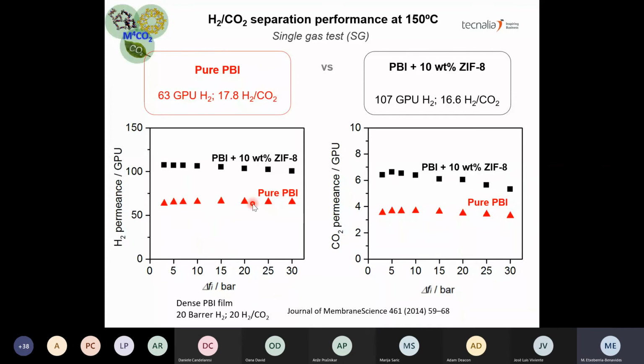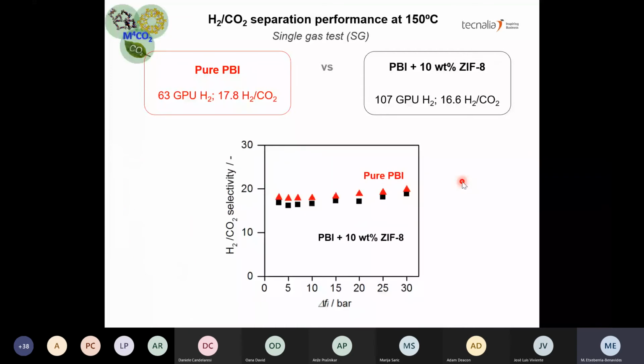In the case of the mixed matrix membranes, the hydrogen permeance was not influenced by the feed pressure, but the CO2 permeance slightly decreased as the feed pressure increased. And this results in a slight increase in hydrogen/CO2 selectivity as the pressure increases. A selectivity around 17 was obtained both for pure PBI and for the mixed matrix membranes.